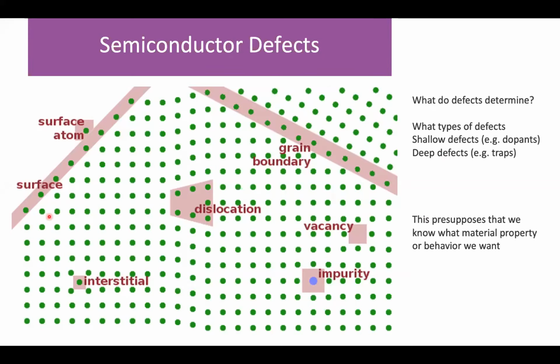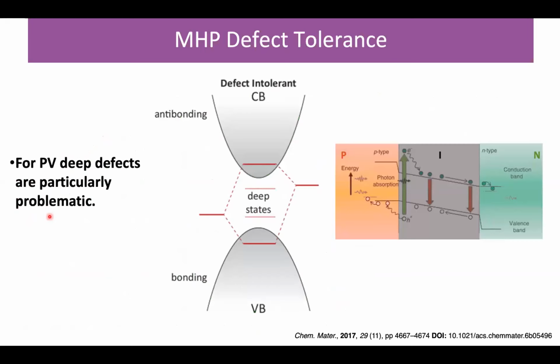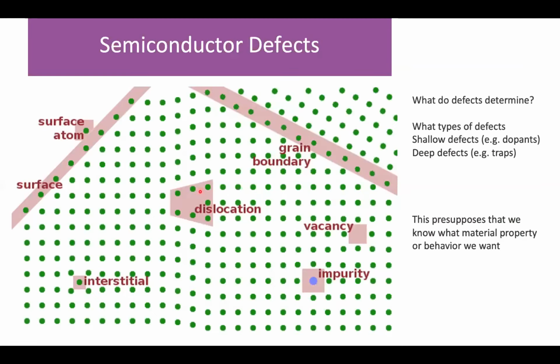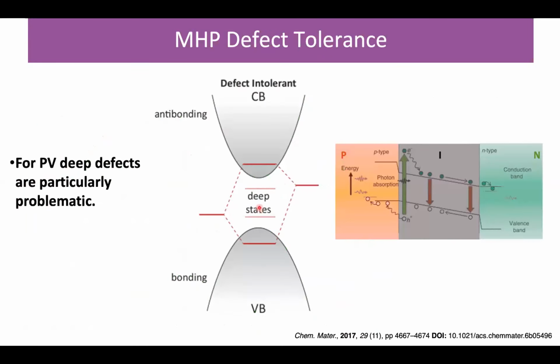At the same time, we also have these kind of things like surfaces. Well, the metal halide perovskite systems, they're solution processed. The resulting materials are not single crystal. They're horrible polycrystalline messes, but yet they have these efficiencies that beat all the other thin film materials. And so the question is, well, why? The property that they have that's kind of unique is the property of defect tolerance. As I just laid out, when we have these kind of defects, particularly things like dislocations and vacancies, typically what will happen in a semiconductor like silicon is that you'll create deep states inside the electronic gap. Now, in the context of what we need to do for a PV system, that means instead of being able to extract these carriers, we're creating pathways for additional recombination that undercuts our efficiency. And indeed, if we have a lot of these, we'll turn a material that's a reasonable semiconductor absorber into a hunk of garbage, basically, as a material.